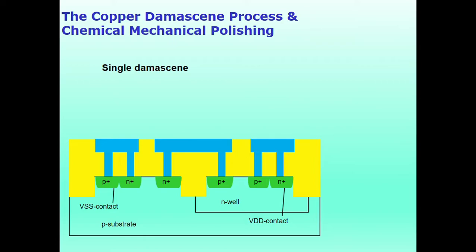Deposited titanium nitride is conventionally used as a copper diffusion barrier. A thin copper seed layer is then sputtered, followed by bottom-up copper electroplating to achieve void-free metallization of complex nanopatterns. Finally, excess Cu plated in the field region is polished away using chemical mechanical polishing.